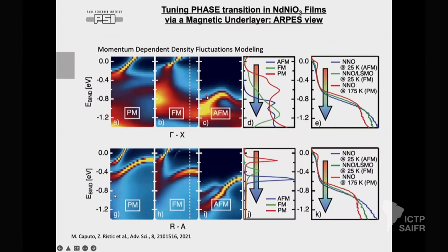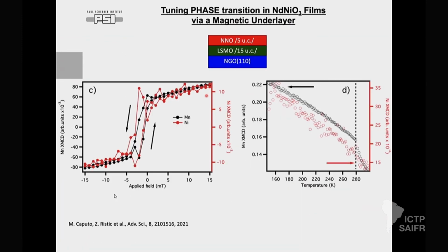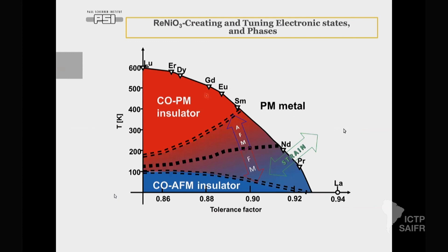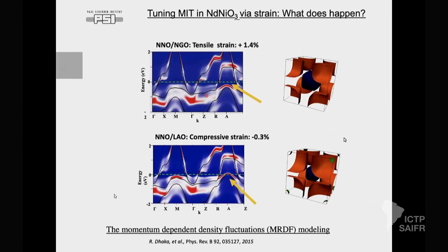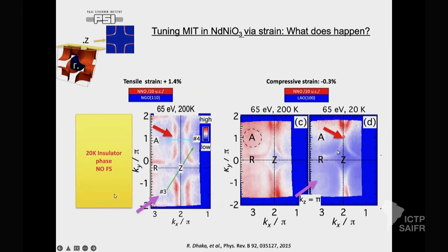And then if I go now here, right. So it's true that the spectral weight here is much lower compared to here. You could see. So that means the correlation is increasing, quasi-particle weight is decreasing. So that means that there is a change toward insulator. The system is not yet an insulator. Maybe it will be an insulator at 5 Kelvin completely. But why is the resistivity going up? Because the localization is increasing. So there is an effect of localization for sure.